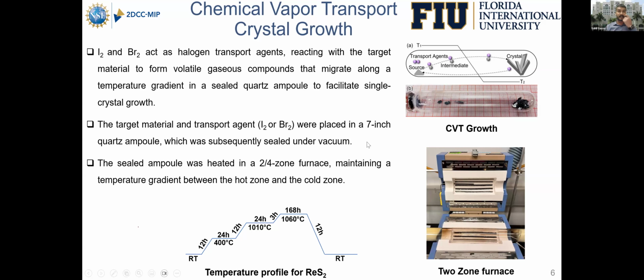So the target material and the transport agent were placed in a 7-inch long quartz ampule, which was subsequently sealed under vacuum. For this, we need a long tube, because we are using a tubular furnace, in comparison to the other furnace which we have used, like the muffle furnace for the flux growth and the melt growth. So for the tubular furnace, we need a long tube to grow the crystals. And again, the sealed ampules were heated in a 2-zone or 4-zone tubular furnace, maintaining a temperature gradient between the hot zone and the cold zone.